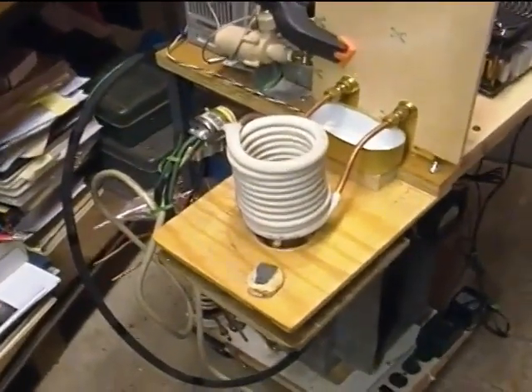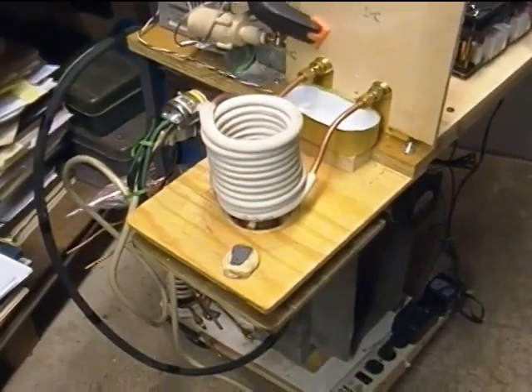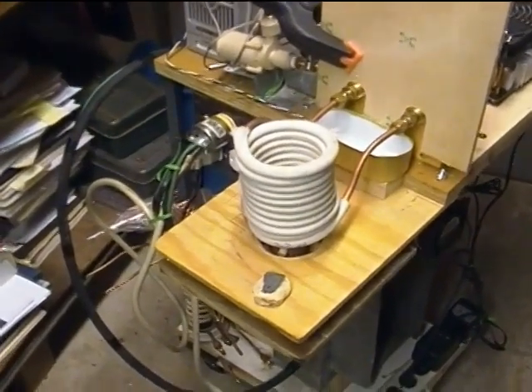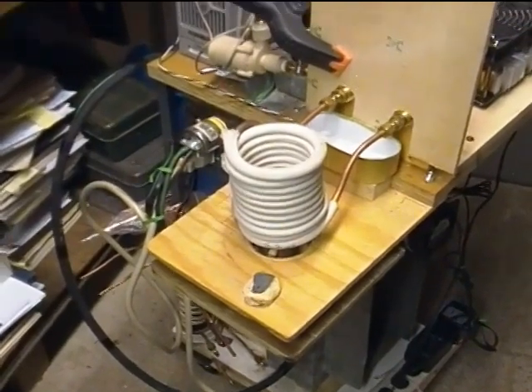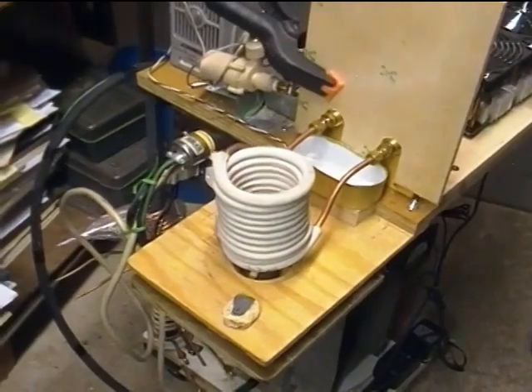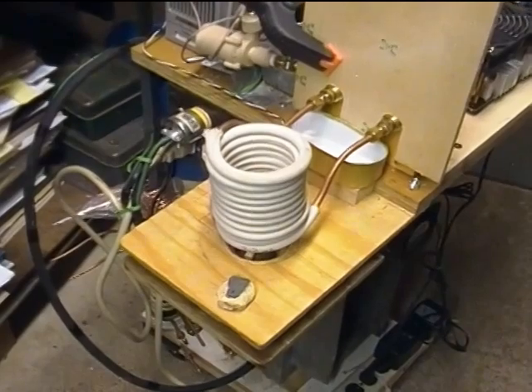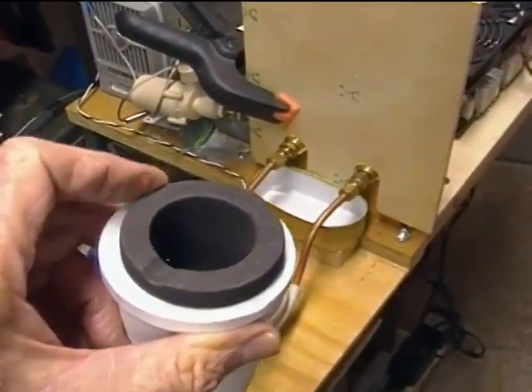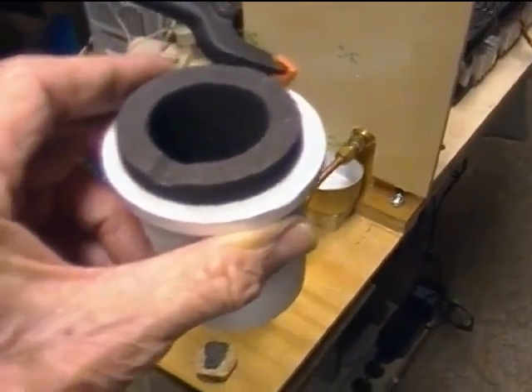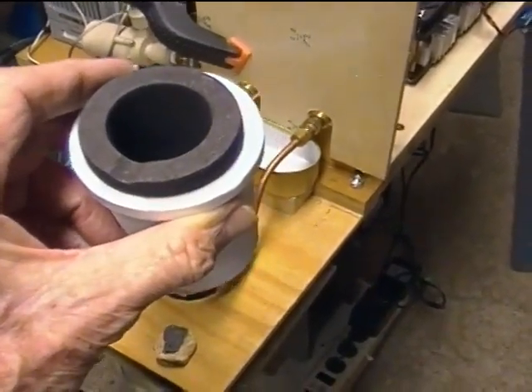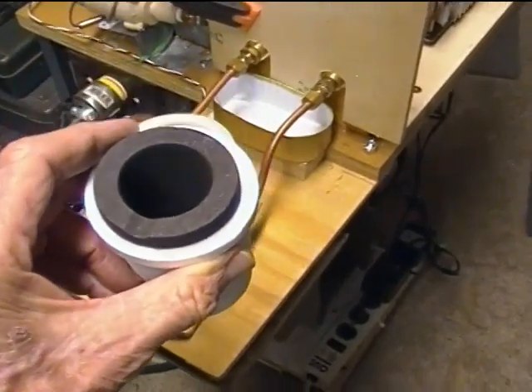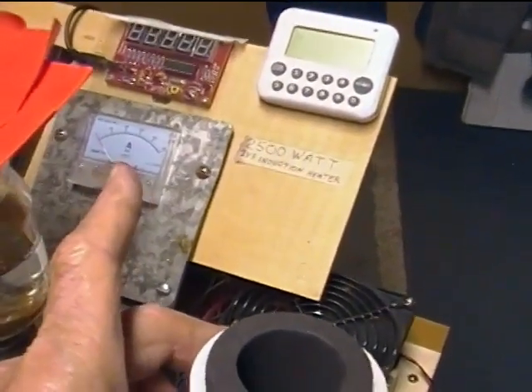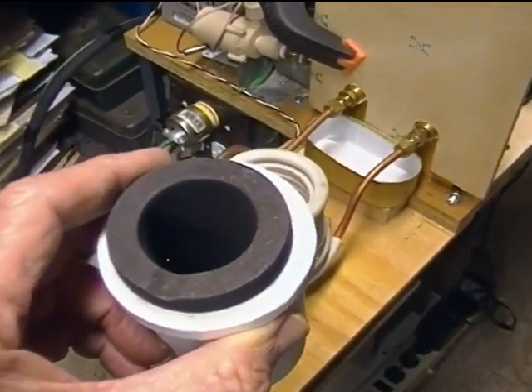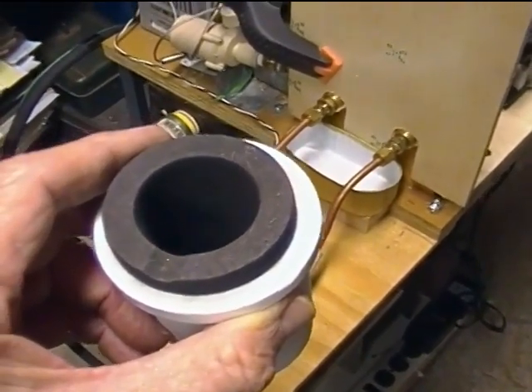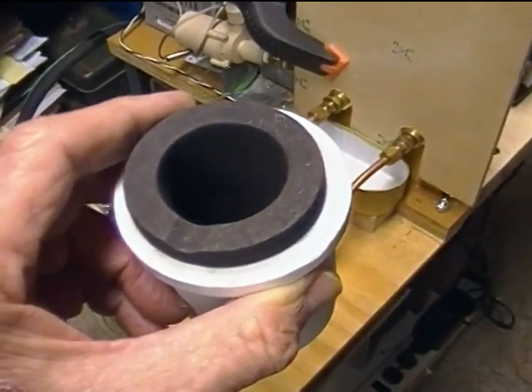And then, in the case of ferrous materials, as we know, once the ferrous material reaches the Curie point, the current drops significantly by maybe as much as half or so. And of course we don't want that because we really want to melt this cast iron. So the idea here is that I will make an experiment, which you will see, and we will see how far I can stick the filled crucible that you saw at the early part of this video when I was showing the mold in the sand, how far down we can place it safely, and then as we reach the Curie point, we'll be able to lower and lower and lower the jack, watching the current all the time so we don't exceed maximum safe current. And then hopefully at some point we'll be able to melt this cast iron and maybe even get it a couple of hundred degrees past melting so that we've got time to pour it into the mold. So you and I are going to see if this works or not at the same time.